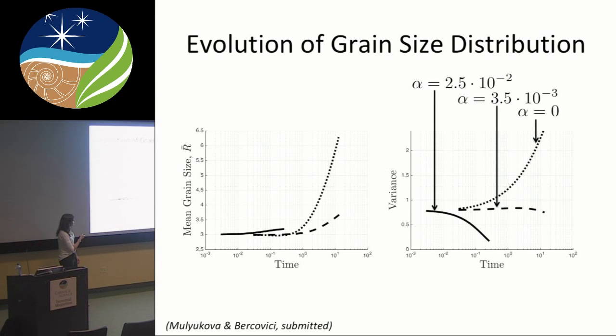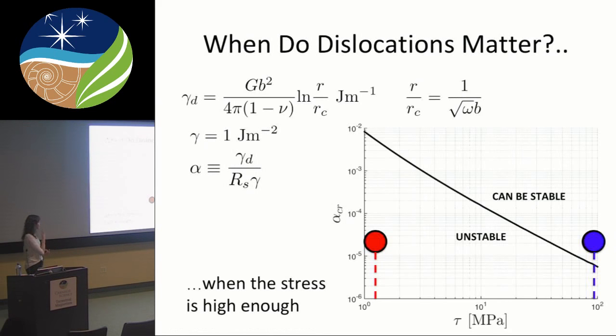If alpha is slightly bigger, I'm still having a smaller increase in grain size, but my variance is not changing very much. And then finally, this somewhat radically different behavior where my grain size is increasing very little, but my variance is actually decreasing. So I'm collapsing my grain size distribution function. So seeing that in actual reported mineral physics experiments would be very helpful to see if there's any truth to it. Okay, I've reached the last part of my talk.